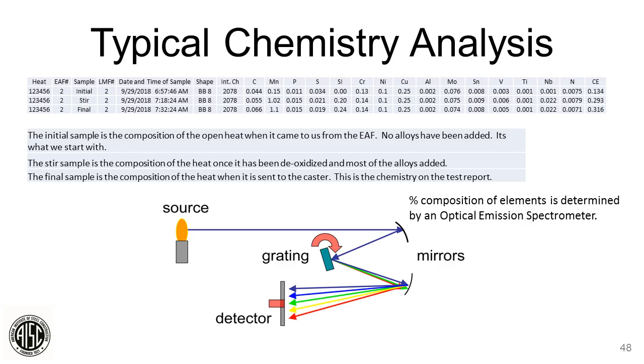So this one's kind of interesting, and I hope you bear with me, but what we do here is we use optical emission spectroscopy to analyze the steel chemistry. So periodically during the processing of the heat, we'll stick a sampler into the steel and create a steel lollipop, which we grind. We'll put it on an optical emission spectrometer, and basically an arc is generated between the electrode in the machine and the steel sample, and diffraction of the light breaks it down to individual wavelengths of the element you're looking at, hits the detector, and we know what our steel chemistry is. It's a pretty powerful tool, we use it every day.